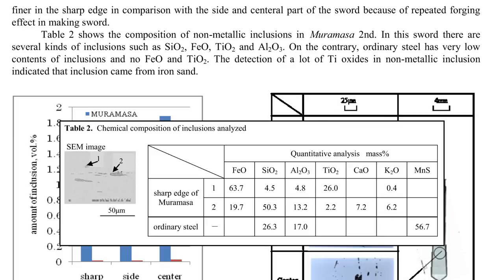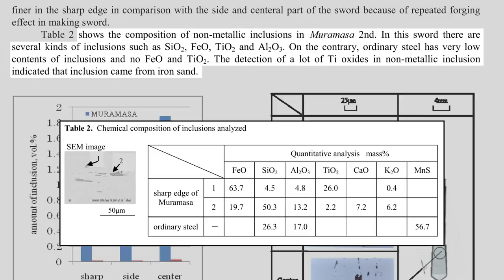Now, table 2, so have a look at the table, shows the composition of non-metallic inclusions in Muramasa II. In this sword, there are several kinds of inclusions, such as silicon dioxide, iron oxide, titanium dioxide, and aluminium oxide. On the contrary, ordinary steel has very low contents of inclusions and no iron dioxides and titanium dioxides. The detection of a lot of titanium oxides in non-metallic inclusions indicates that inclusions came from iron sand.